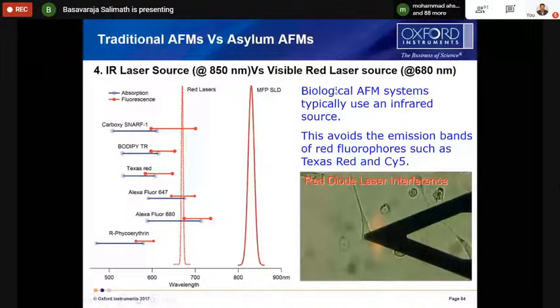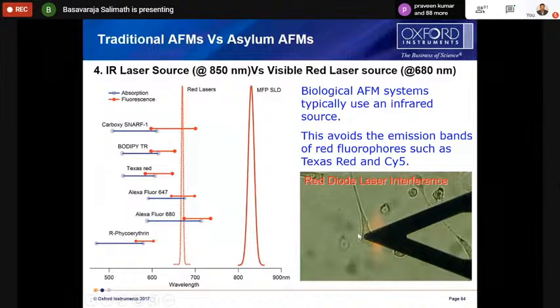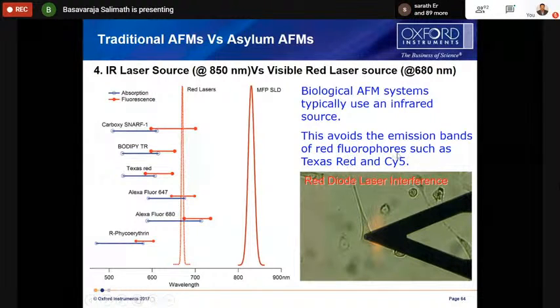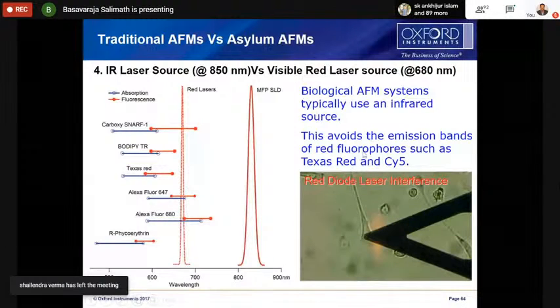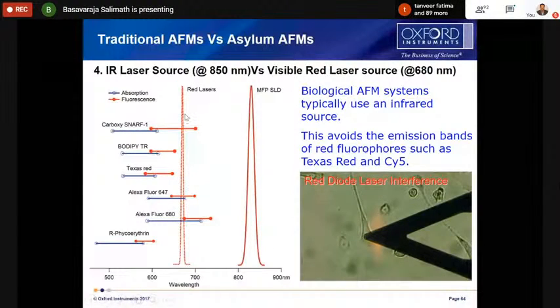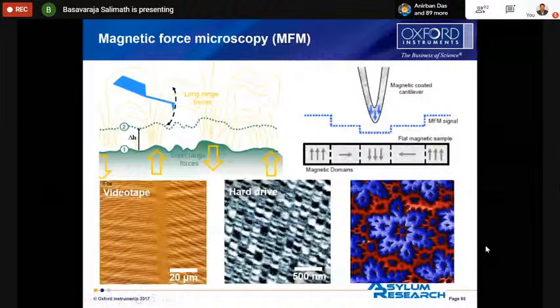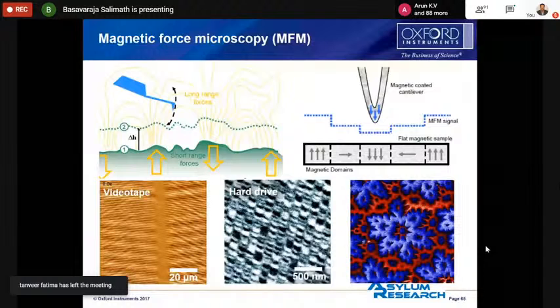And also one of the disadvantages of this visible red laser is that if you are doing a kind of inverted AFM with an inverted microscope, you have some cells, and you add some fluorophores to see them clearly in the fluorescence microscopy. But these cells will absorb these red lasers, whatever fluorophores you add, so you won't get any fluorescence images in the fluorescence microscopy, and you can't recognize these cells. Whereas these SLD lasers will be a little bit above, around 850 nanometers, so this kind of problem you don't face with Asylum Research AFMs. So that's about traditional AFM versus Asylum AFM.